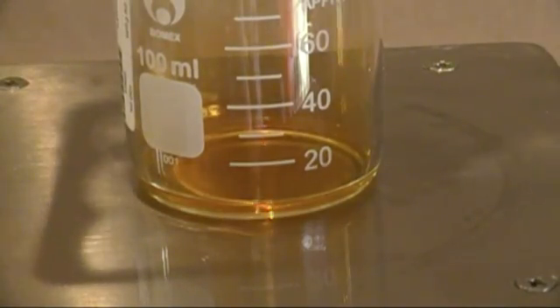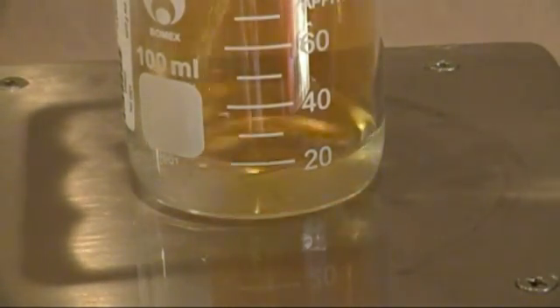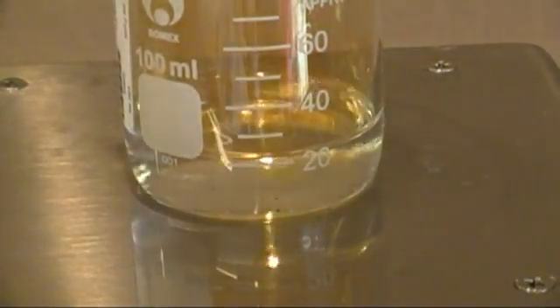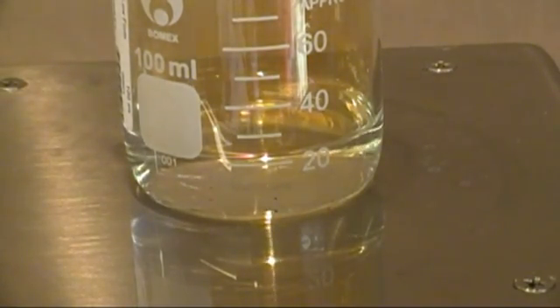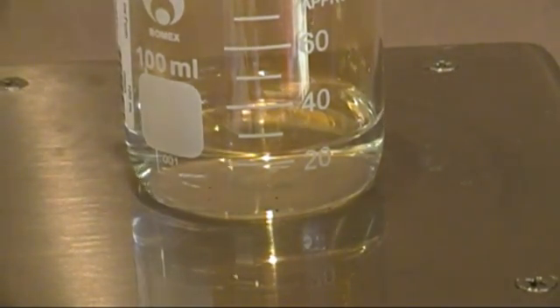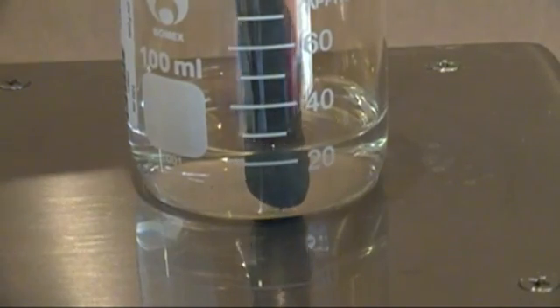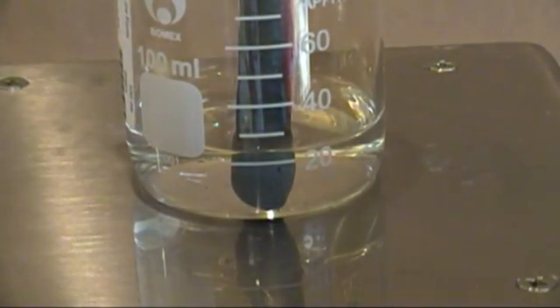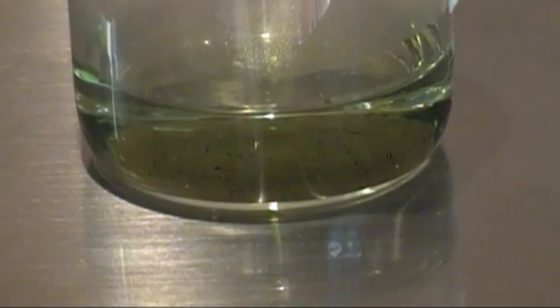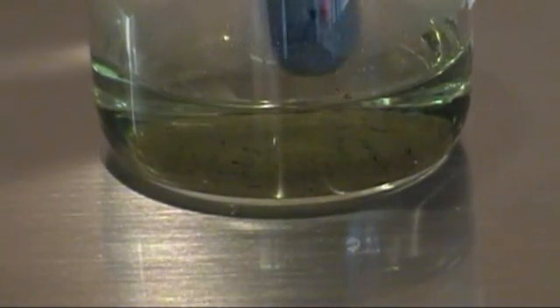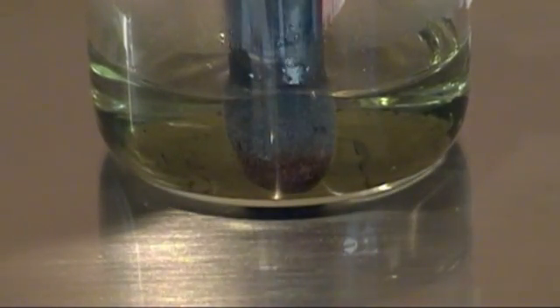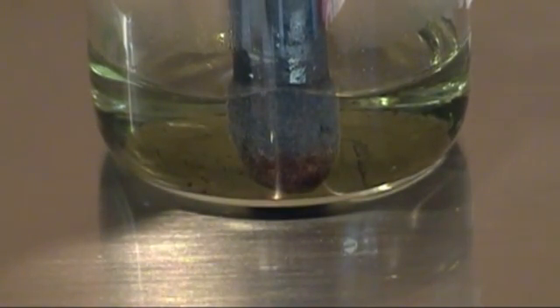So let's up the ante. Here's fuming nitric acid. I'm going to add a small amount of water so we can see the reaction. Now I drop in the epoxy. And nothing. It does not seem to be reactive towards nitric acid either. I save the best for last. Here's 98% sulfuric acid. I'll put the epoxy in. And now we get a reaction. So 98% sulfuric acid will react with the epoxy.